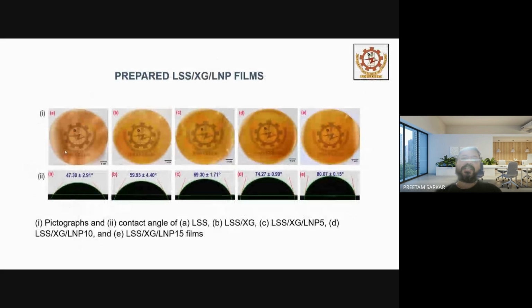What we do here is prepare bioactive films or coating systems by the most standard, easy, simple technique, called the solvent casting technique. For the first film, we have LSS, that is lychee seed starch alone. For the second film, we have lychee seed starch with xyloglucan in a 1:1 ratio. The third one, film C, is LSS XG LNP5, that is 5% lignin nanoparticles, then 10% lignin nanoparticles, and 15% lignin nanoparticles. Now, when we talk about these bioactive packaging materials, one of the very important criteria we have to look at is the surface hydrophobicity.